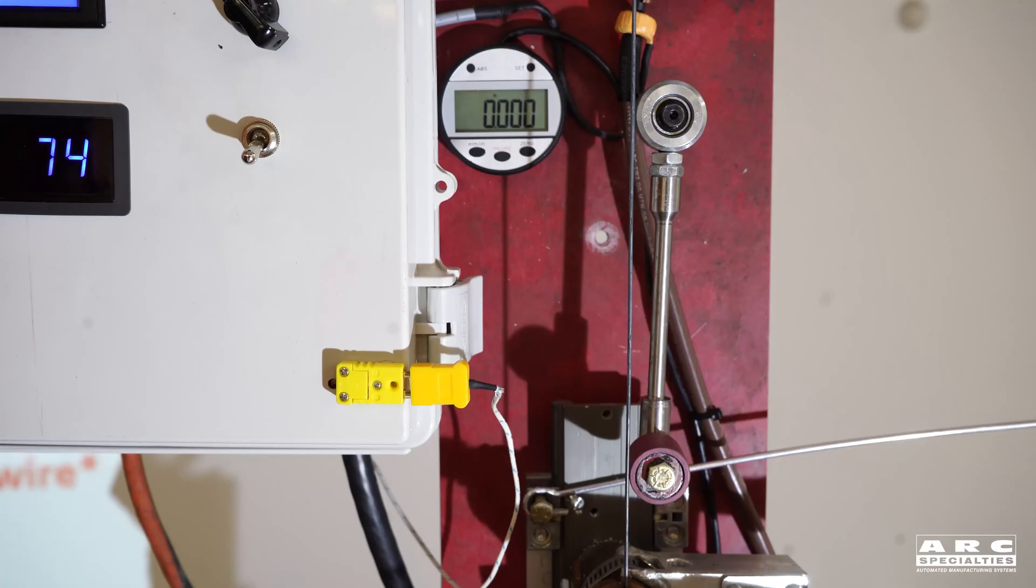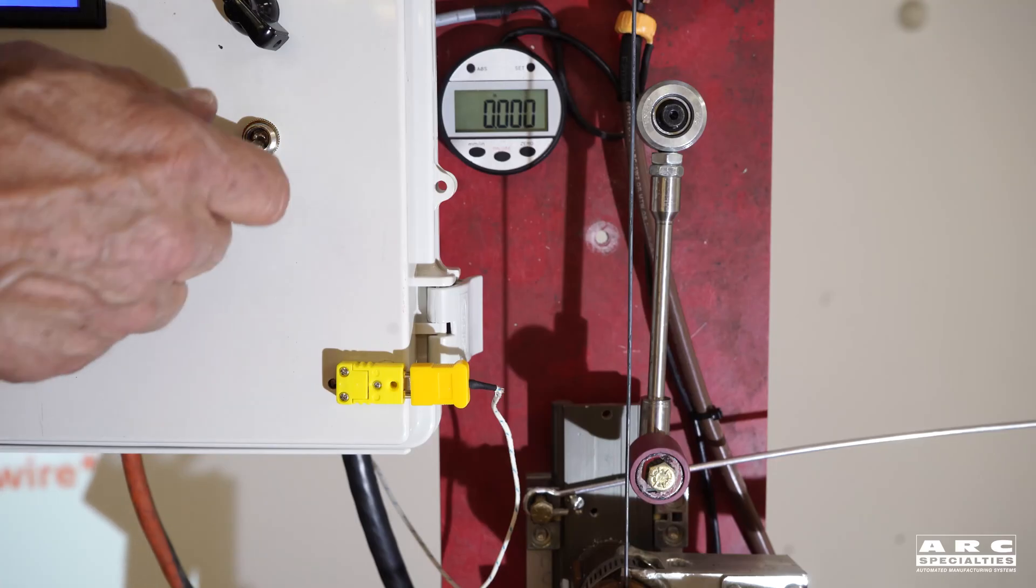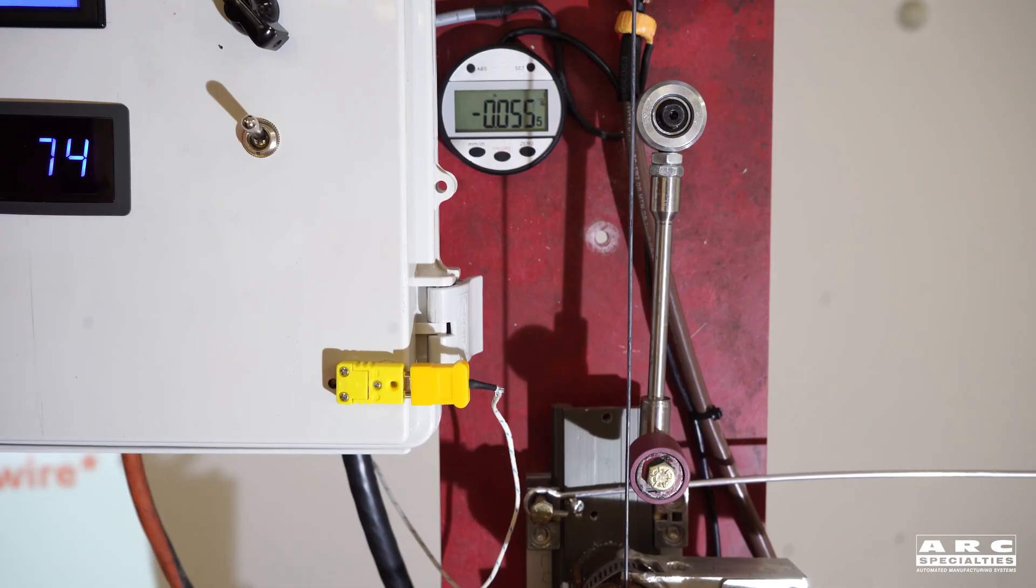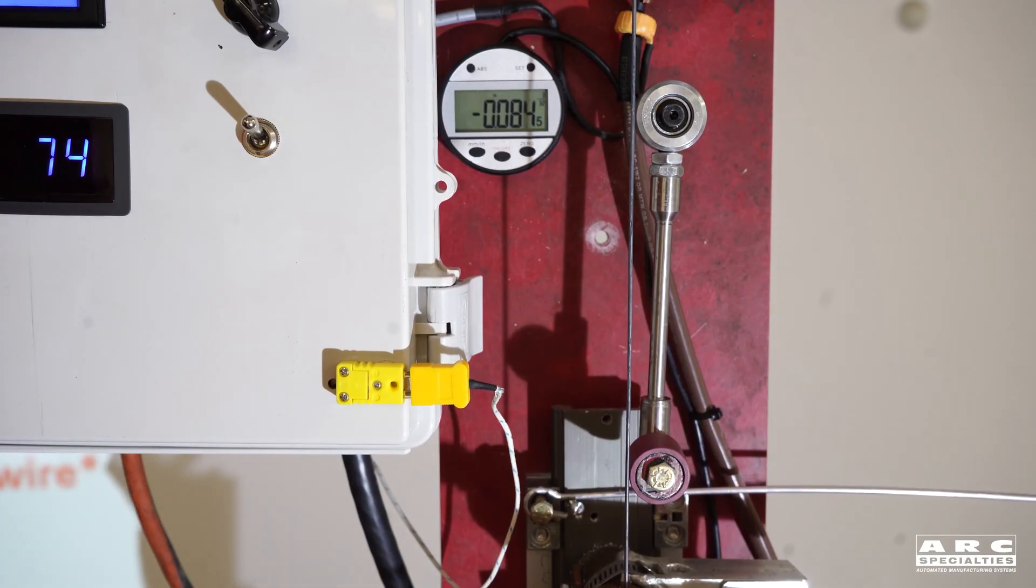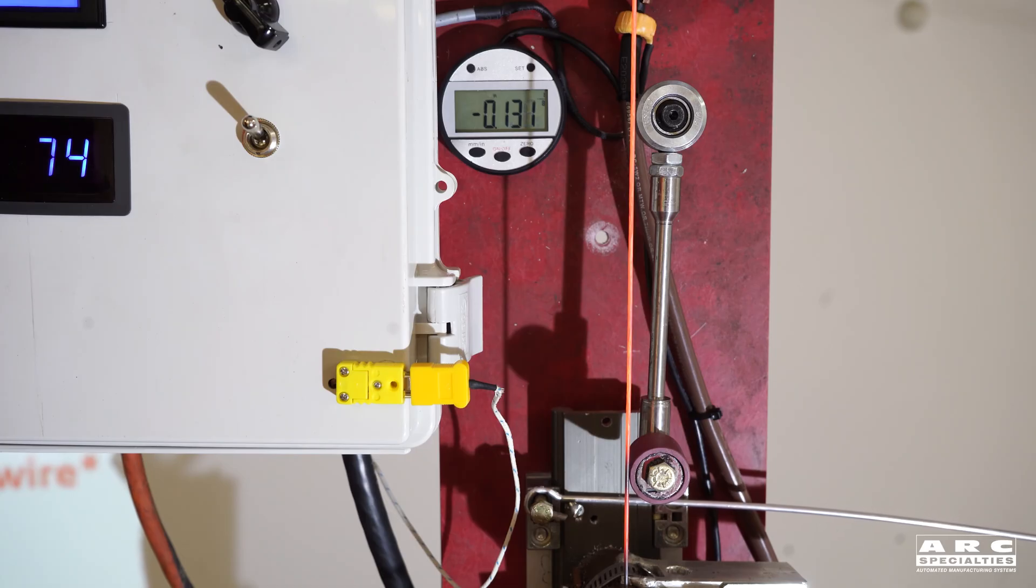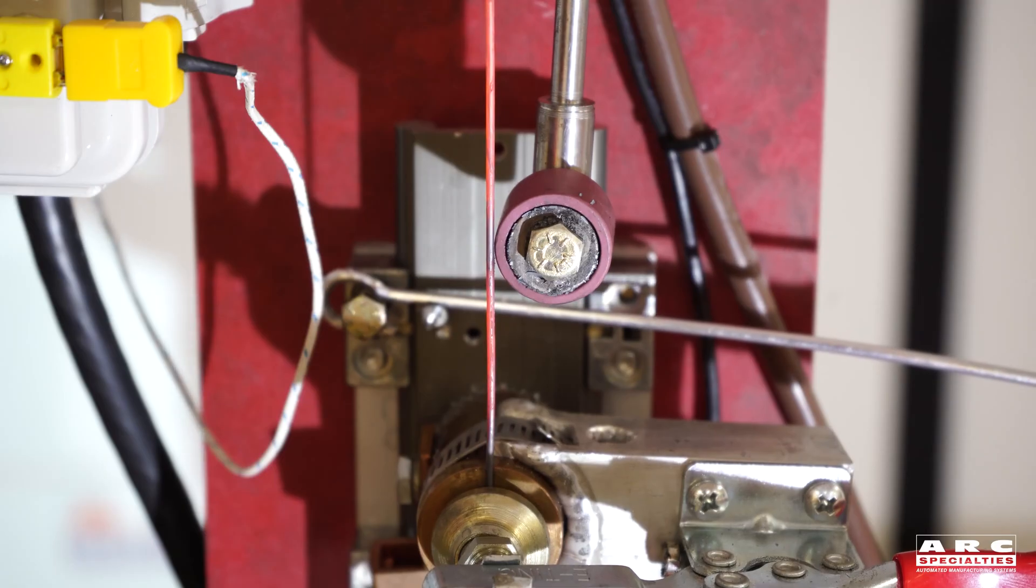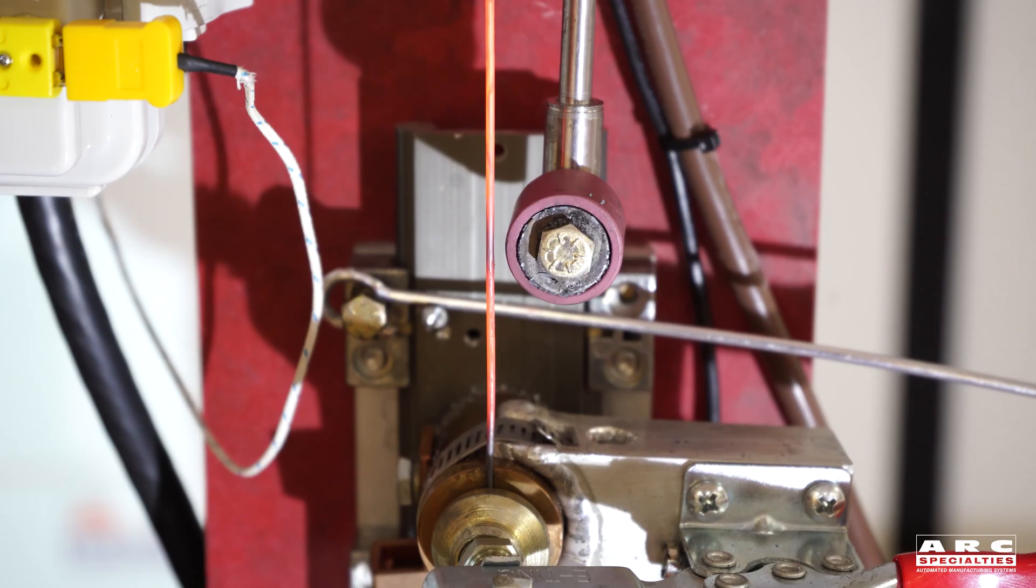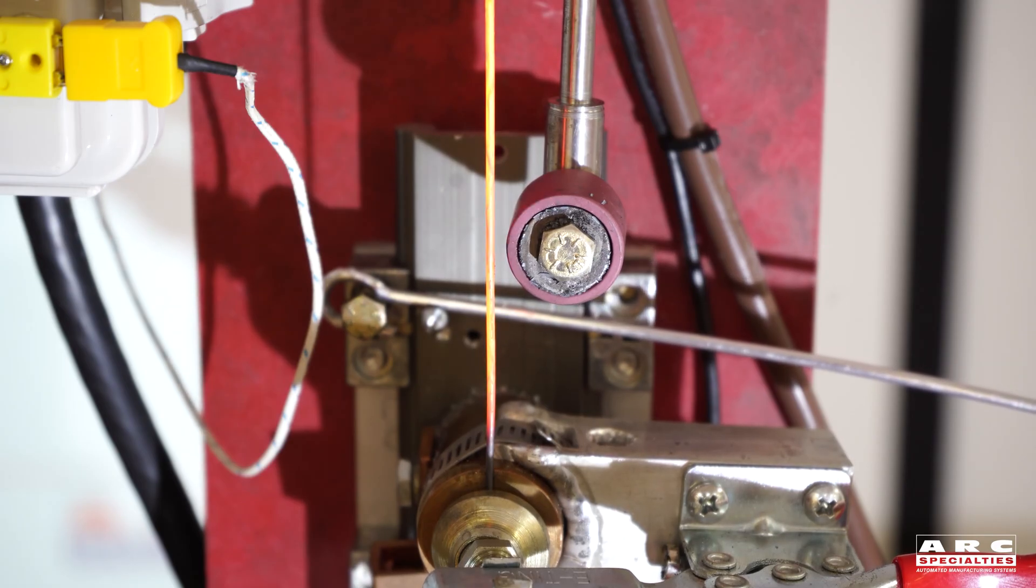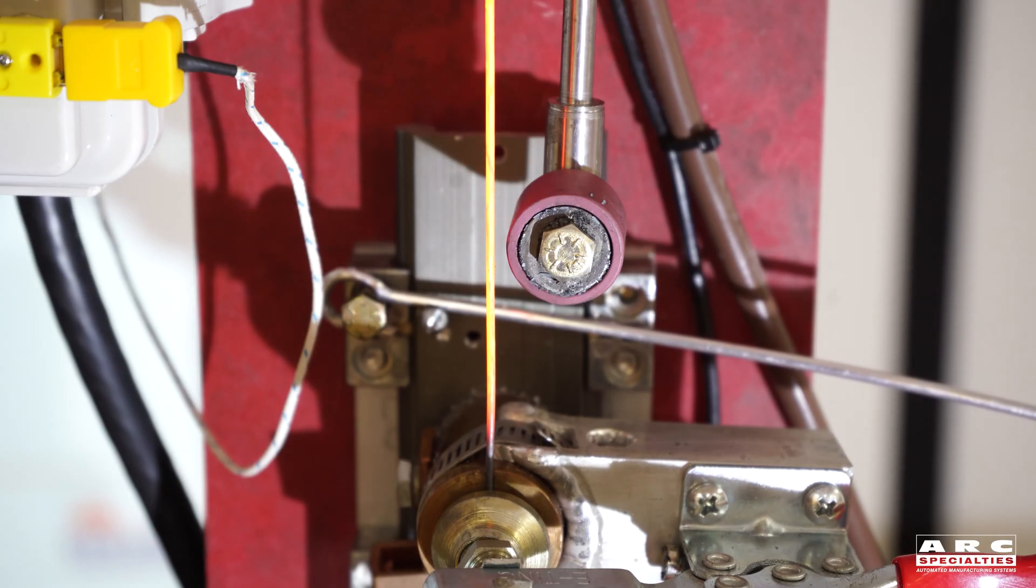So as we heat this thing up, you're going to see several phenomena. First is color change. As we heat it up, the wire is going to start to glow red. The old blacksmiths know that around 1,000 degrees in subdued light, you'll start to see red. So now we see red. We're heating higher. Right now the magnet's still sticking to the part. There, the magnet fell away. So we've austenitized the part. We've gone from body-centered cubic to face-centered cubic, and you can tell because the magnet's moved away from the part.